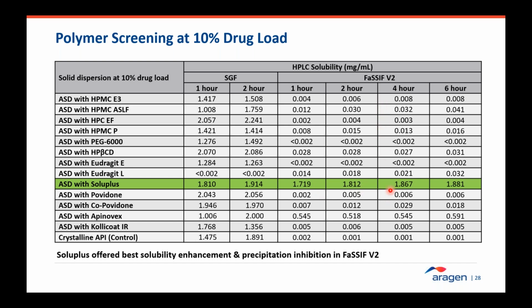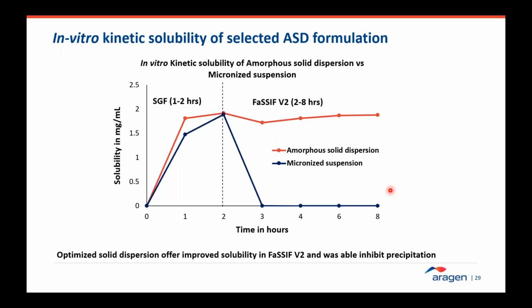in FaSSIF. And we further optimized it, increased the drug load, optimized with a combination of surfactants, and conducted the same solubility studies. So here you can see that the micronized suspension also dissolves in low pH due to its inherent solubility of the crystalline drug. But when we change the pH, it rapidly precipitates, simulating the GI tract event, how it happens when the dosing happens.